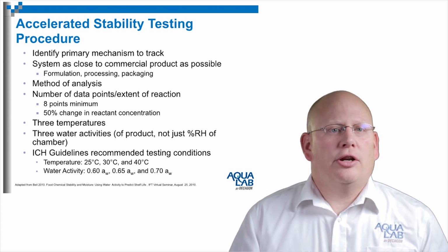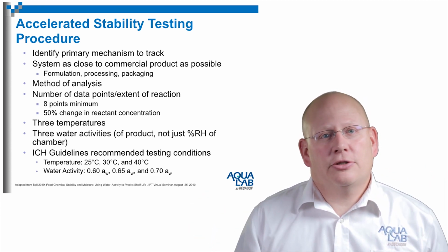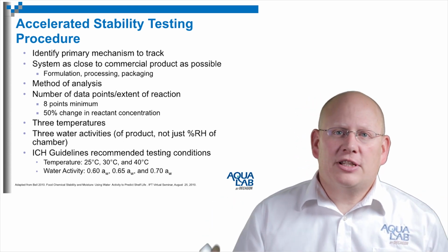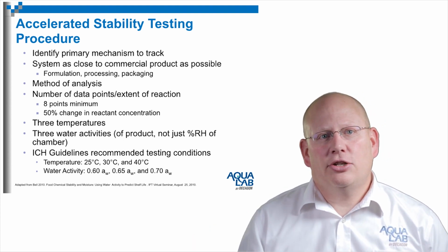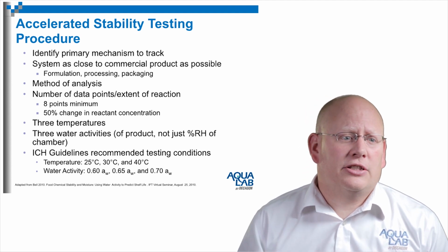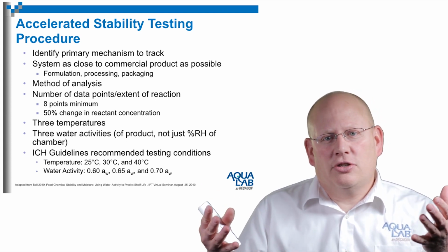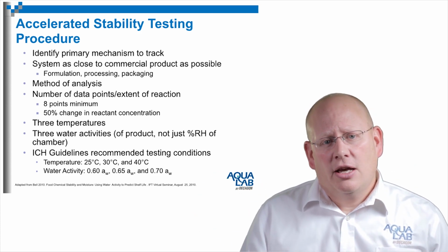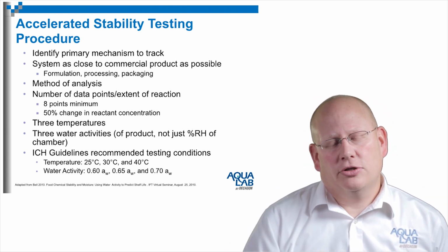And all of this is associated with, if you want to, as part of a drug release program, do what's called accelerated stability testing, which is kind of a new buzzword in the pharmaceutical industry, to be able to establish what the stability is without having to wait for an entire year to do real-time stability testing. This has been done for many years in the food industry, called accelerated shelf life testing. But the idea here is that you increase the conditions that a product is exposed to, trying to speed up all the processes that could happen, the degradative reactions, and then try to model that and extrapolate back to what it would be under normal conditions.